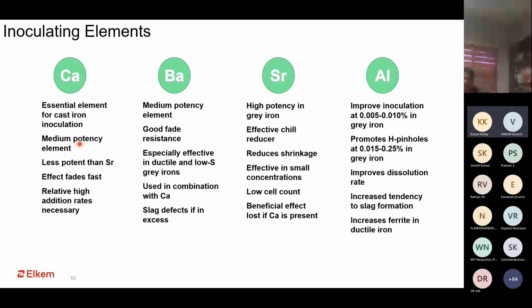It is a medium potent inoculant. It does not have a very strong potency. It has a much faster fading rate, so it fades pretty quickly. And if you're using a calcium inoculant, definitely you have to add a lot more inoculant into the system.